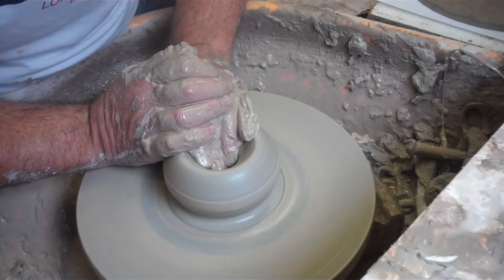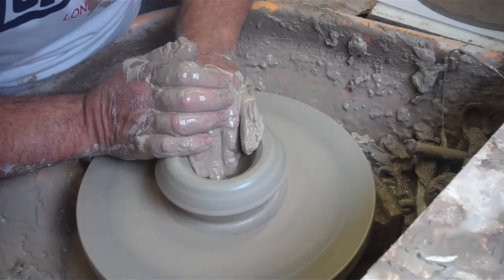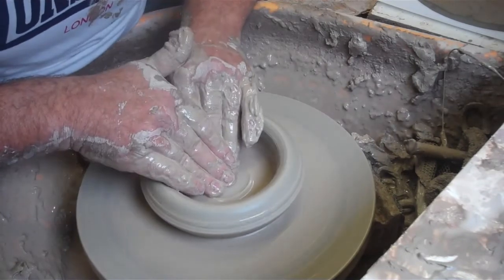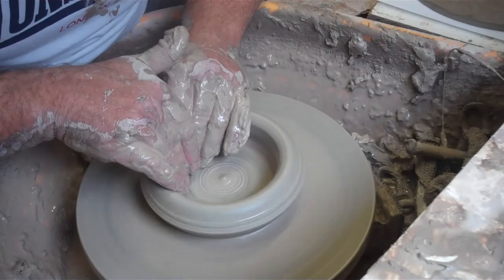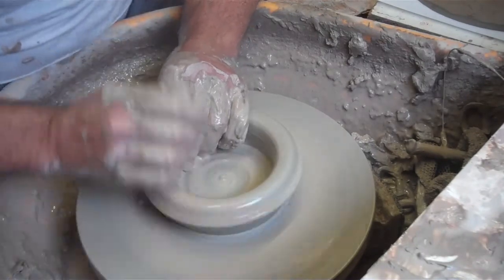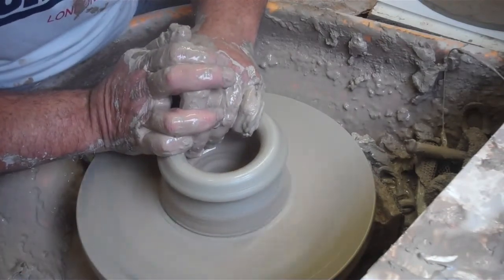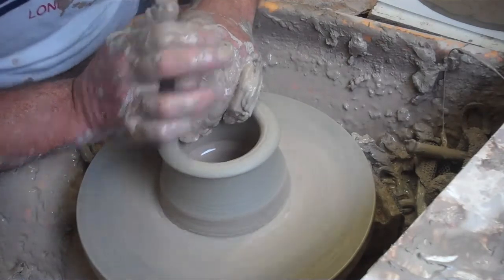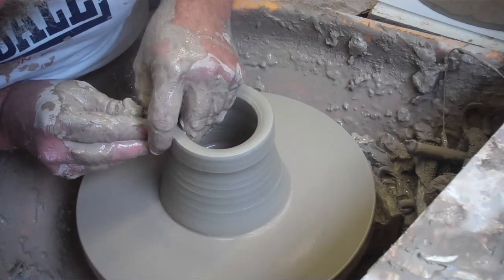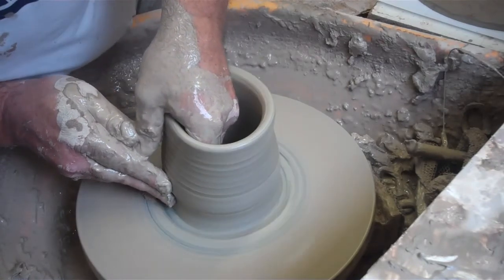This clay, it's the usual crank clay, but it's got some very smooth white stoneware mixed into it. And it throws a lot nicer. That's a friend of mine, Alex Shimwell. It can be a bit short, this crank clay. It's alright for big moon jar type pieces or big slab type pots, but it needs to be a little bit more plastic. So I've mixed an extra smooth white stoneware in with about 20%. And so far so good, it's been throwing lovely.